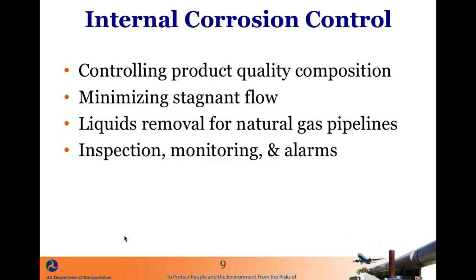So another way is to minimize stagnant flow in a line. If the product's always flowing, pretty much corrosion will not localize in one place if the corrosion products are constantly moving. For natural gas lines, it's important to remove the water, because without water, really, natural gas line corrosion does not occur. And there's also frequent monitoring inspections which take place. And that's a very important part, because if you don't look for it, you won't find what you're not looking for.